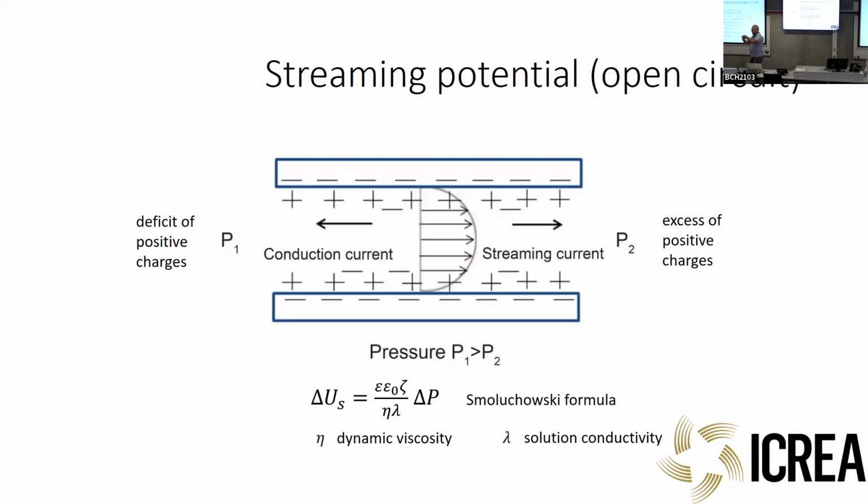But when the pore becomes a real nanopore, then these charges, compensating fixed charges, take up ever larger volume of the pore, and then the conductivity is increased. This phenomenon is called surface conductance. I think it's not so difficult to understand that if you increase the surface charge density, then both the streaming current and surface conductance increase, because you have more charges that move.